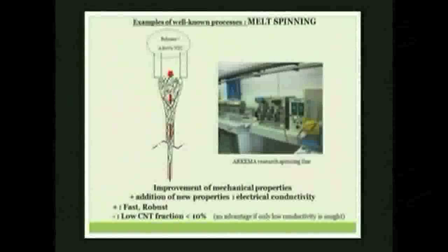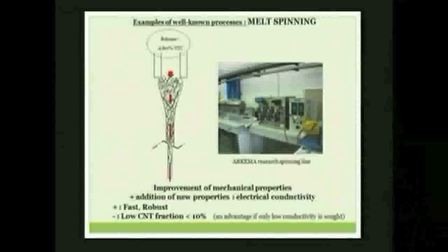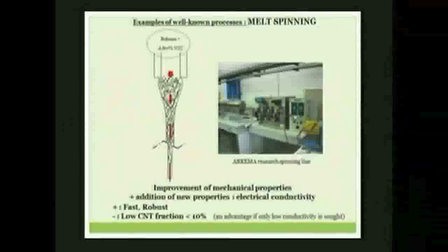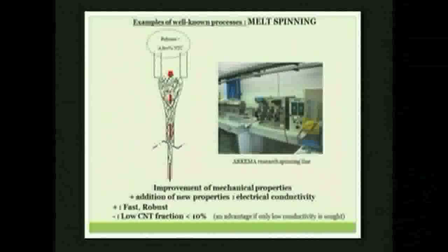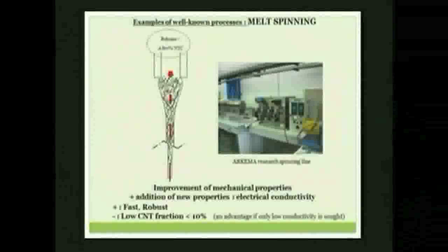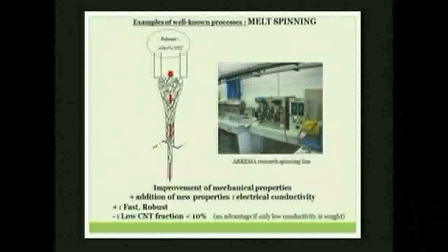Among well-known processes, you find what is called melt spinning. It's a very industrial and well-known process in which you mix the polymer with a few percent of nanotubes, and you melt this mixture. Generally, you cannot put a lot of nanotubes inside because it becomes very viscous, and it's not possible to process it. This mix of melt polymer and nanotubes, you extrude it like this, and you can make fibers with this process. But as I said, it's fast, robust, but you cannot increase the quantity of nanotubes. Okay, so you have limitations.